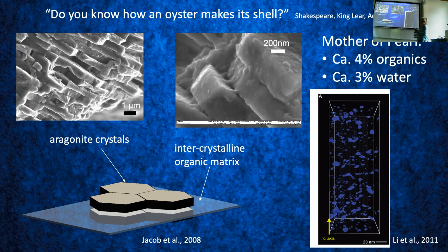Mother of pearl, if you break it and look at it under the SEM, consists of tablets like these. I said they have up to about 4% organics and a bit of water. Going closer, you can just about see that the aragonite tablets have a coating of organics around them. Schematically, you have hexagonal or pseudo-hexagonal aragonite tablets that come in layers, and each of these layers is formed by organic matrix that people thought was chitin. We found it's actually not chitin, it's a silk-like protein, which wasn't known. And also, it's not just in between these layers of aragonite, it's also within the tablets.